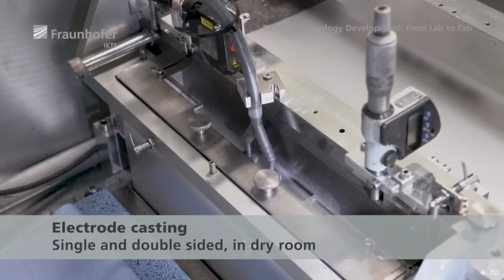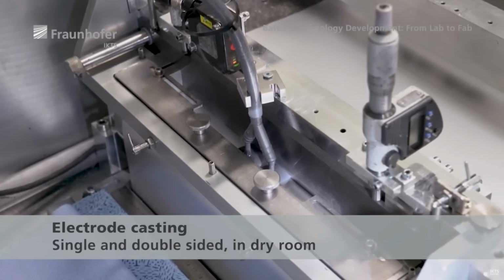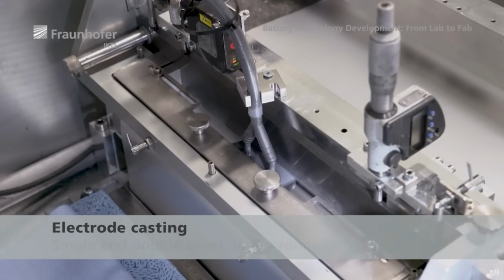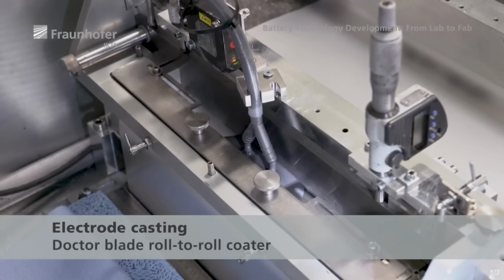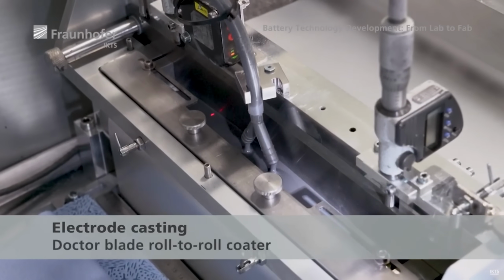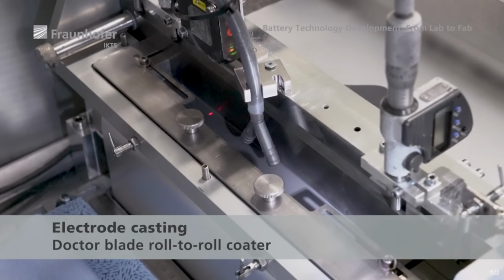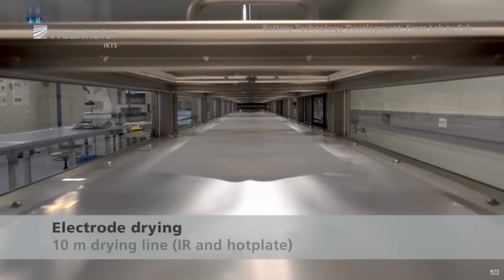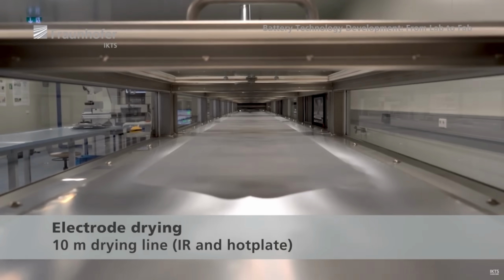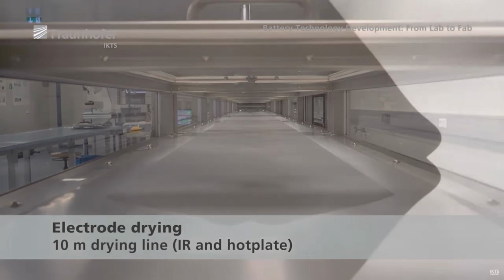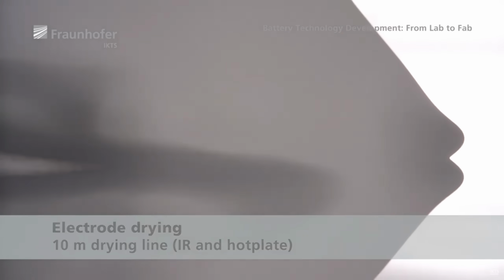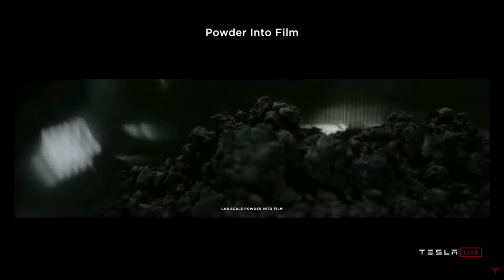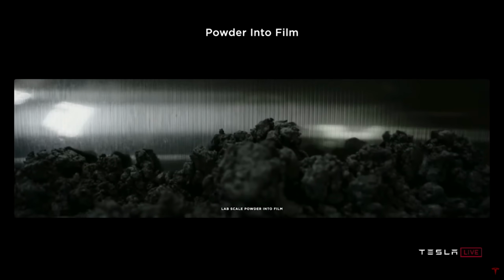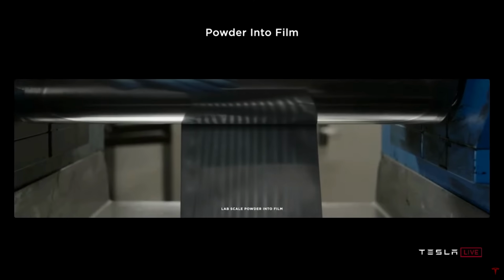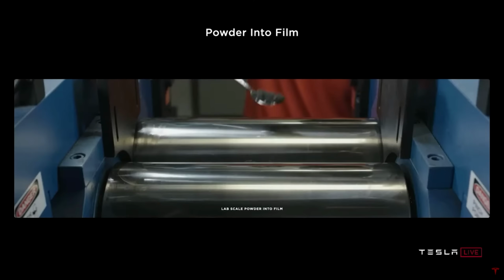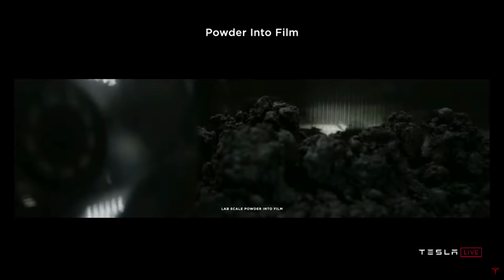As a side note, the reason why a wet coating process can't make electrodes as thick as a dry process is because the wet coating mixture is made up of a solvent, cathode particles, and additives. If that mixture is applied too thick, the particles can sink to the bottom of the liquid before it dries, which renders the electrode unusable. The dry coating mixture, on the other hand, consists of particles and binder that form a kind of dough, which carries no risk of stratification.